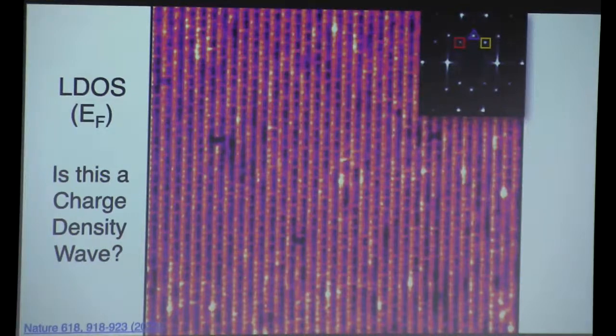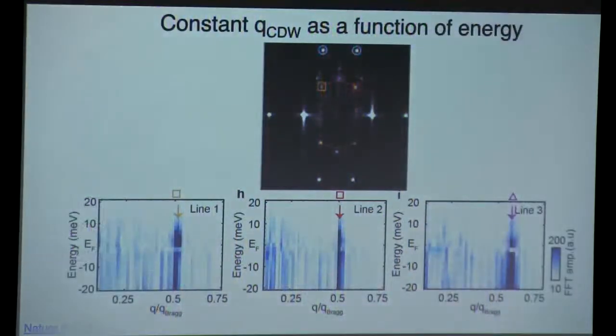You can ask, is it a charge density wave? In STM, one piece of evidence that something is a charge density wave is that its Q doesn't change with energy. You can plot the energy versus the momentum position of each of these Q vectors, and you can see that they don't change. Based on this, we can say that this is most likely a charge density wave.